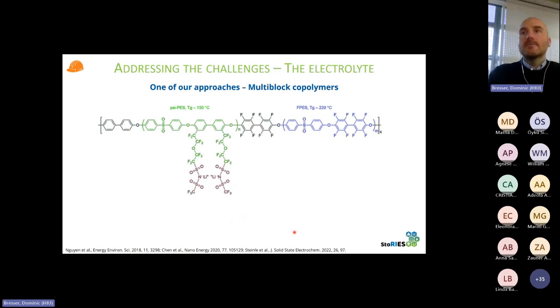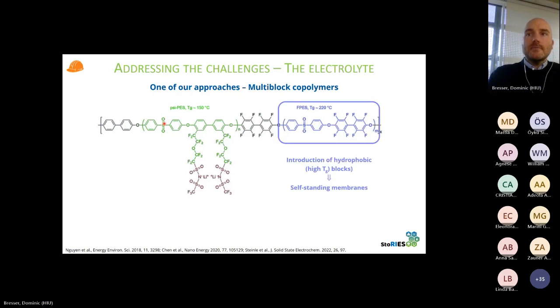And I'd like to just basically show one example here of such single-ion conducting polymer electrolytes. It's a bit more complex, let's say, the polymer architecture. So it's a so-called multi-block copolymer. So you see here the hydrophobic block that we added. So the hydrophobic block plays the role of, let's say, providing suitable mechanical properties, right, with its high glass transition temperature. And we need these properties basically to get self-standing membranes, so polymer membranes that we can easily process.